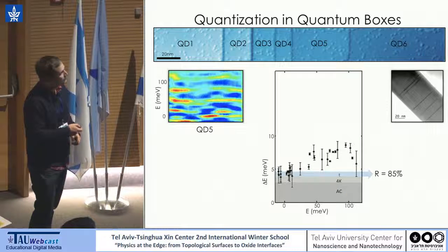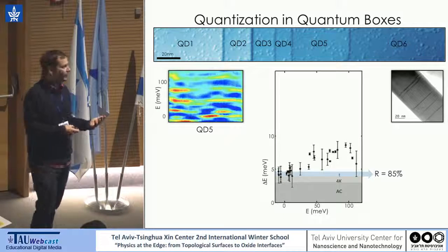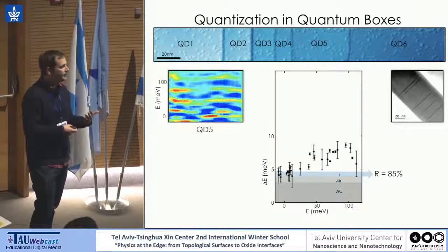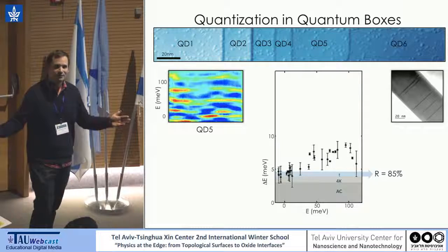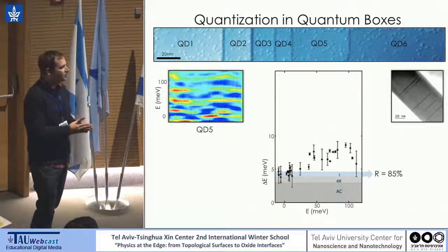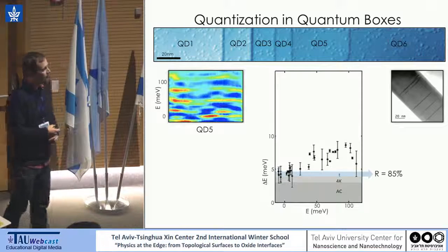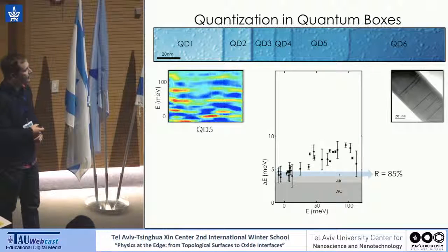From the residual broadening that we get at Fermi, we can extract that stacking faults reflect electrons 85% of the times they hit. So a stacking fault basically cuts the nanowire into two weakly coupled segments. Whoever is doing a Majorana experiment should probably avoid having stacking faults in their nanowires. Now we're left only with the energy-dependent part of the broadening.